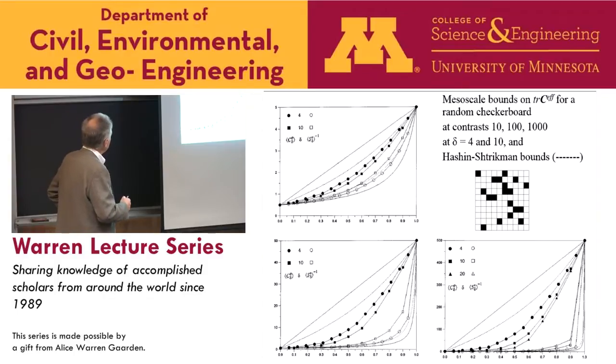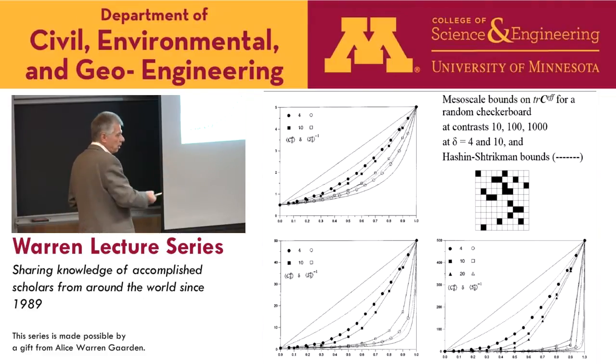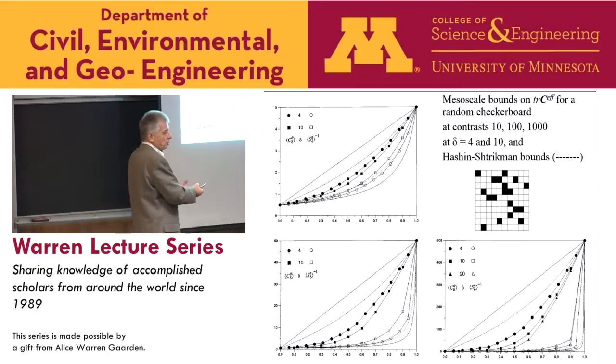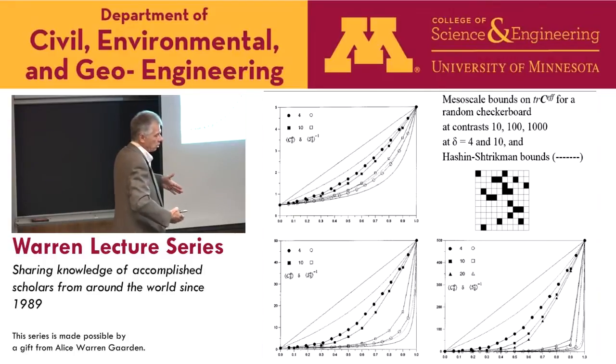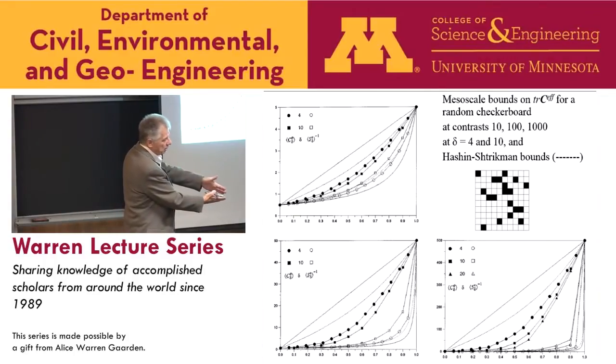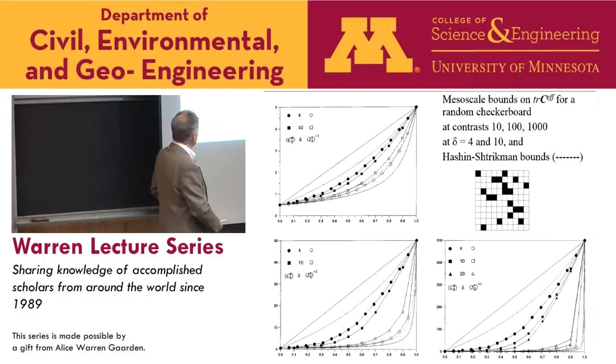And here's the Hashin-Shtrikman broken line, Hashin-Shtrikman lower bound. But if I go with windows that are 4 times bigger, I have circles, 10 times bigger or better, and 20 times better. But to get a unique line, an overlapping of both bounds, I would have to go to infinity. So the nice story about this is that the approach is initially very quick for both bounds, and then they begin to asymptote slowly.